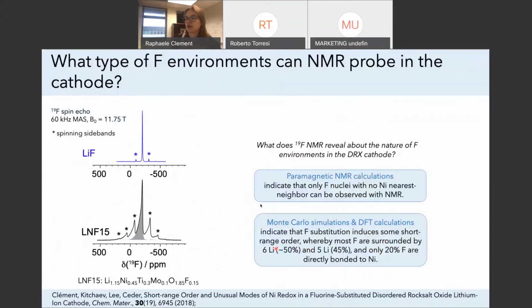So going back to our initial analysis here of this cathode material, we can now say that the spectrum that we see is only coming from fluorine nuclei with no nickel nearest neighbor. This is what we found with our first principles NMR calculations.